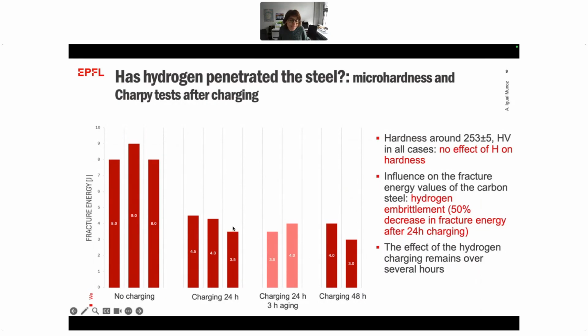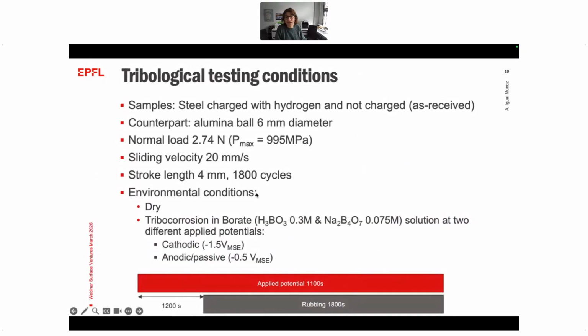On the other hand, the difference in the charging effect when we charge 24 hours or 48 hours was nothing, exactly the same. So with this test, we already know the hydrogen intake, so we can define some tribological testing conditions. We did it in a Taylor tribometer, a homemade ball-on-disc tribometer, under different environmental conditions.